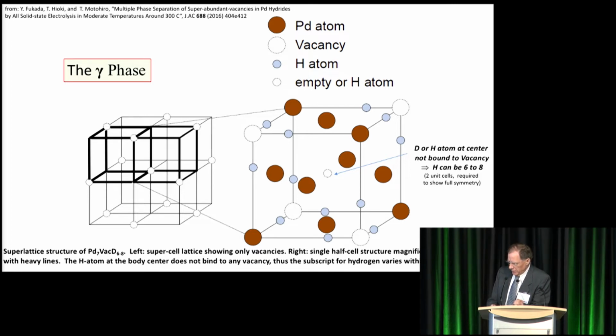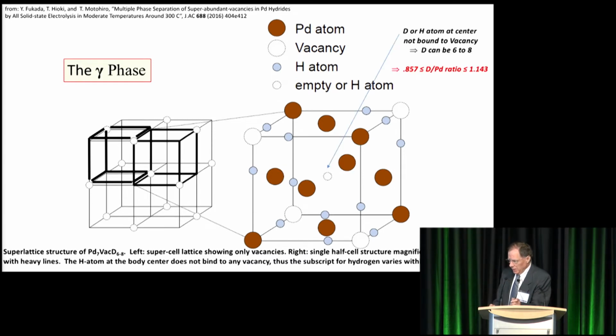So now there's octahedral sites on the middle of the edges, and you can see that the octahedral sites occupied with hydrogen or deuterium have a tendency to shift slightly toward the vacancy. There's that trapping bond in there that is not present in the octahedral site in the center of the cell. So whether this atom or site is filled with hydrogen, or whether it's empty, or whether the other twin component is filled or empty, will give you a range of 6 to 8 on the stoichiometry. So that would mean that the deuterium to palladium ratio would vary from 0.86 to 1.14, depending upon that situation. So that's going to be a range on the phase diagram for the gamma phase.